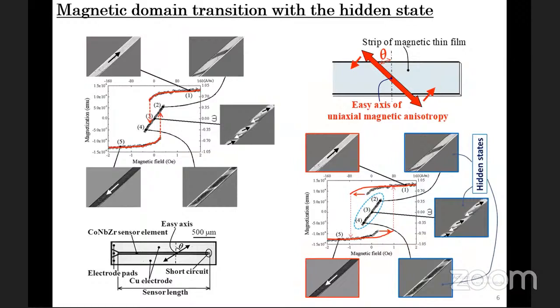These figures are experimentally obtained results. The 60 degrees easy axis makes three states exist around the zero external field, as shown in the left figure. The domain transition that changes to multi-domain, originating from the single domain, appears at the position of the red arrow. When the angle of the easy axis increases, the transition point of the domain state moves, as shown in the right figure.